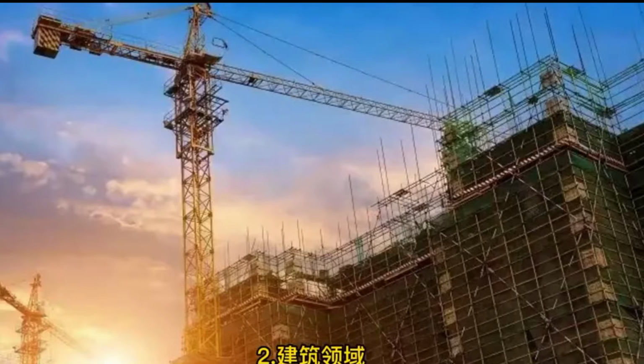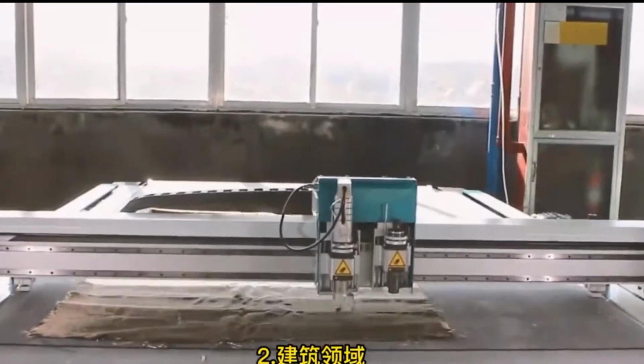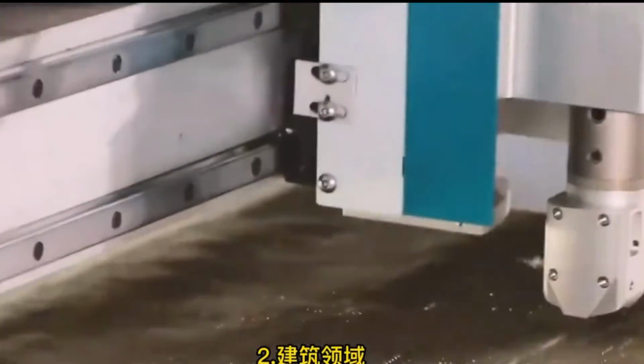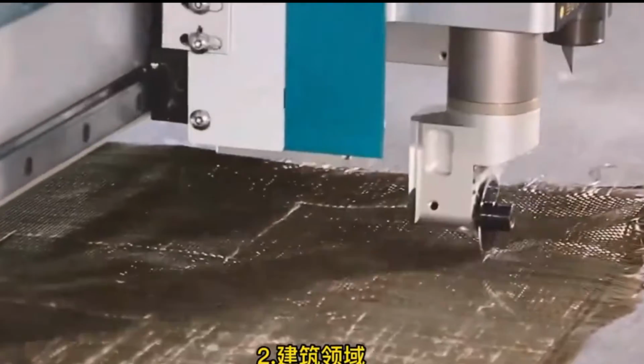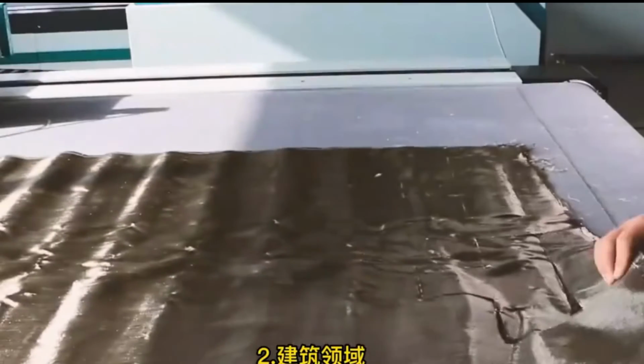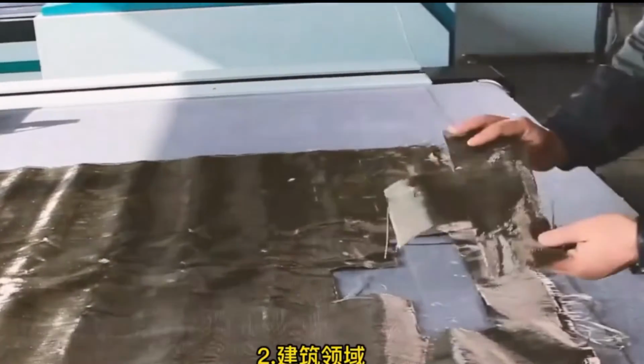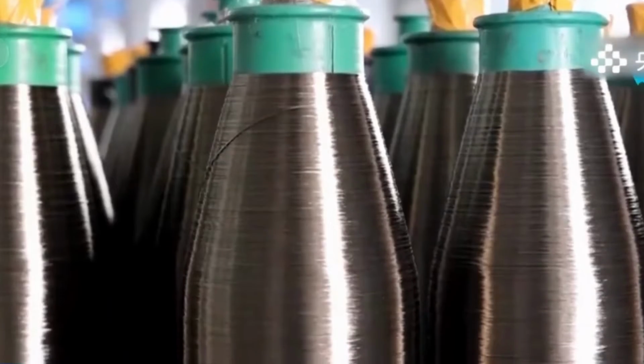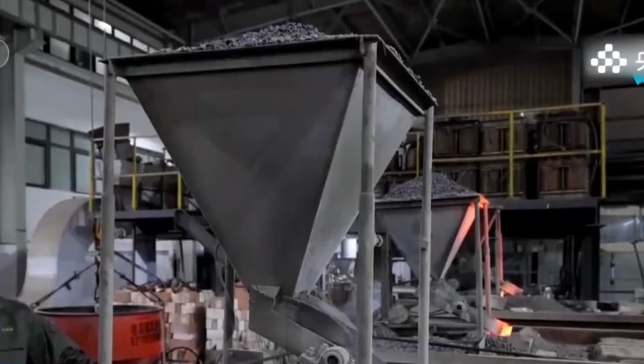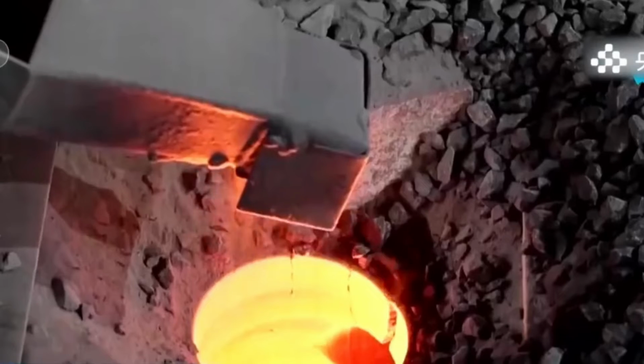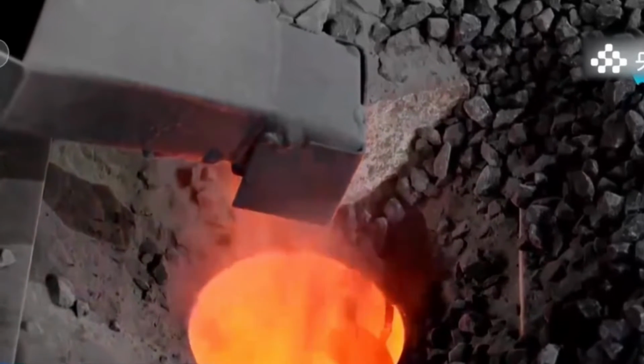Application in the field of fire protection and insulation. Fireproof cloth woven from basalt fiber has high temperature resistance, good insulation effect, no melting and dripping, no toxic gas discharge, and no heat shrinkage. It is an excellent material for fire-resistant clothing, fire-resistant blankets, and fire-resistant curtains, with a temperature resistance of up to 650 degrees Celsius and an ultimate oxygen index greater than 68, greatly superior to organic fibers such as aramid.